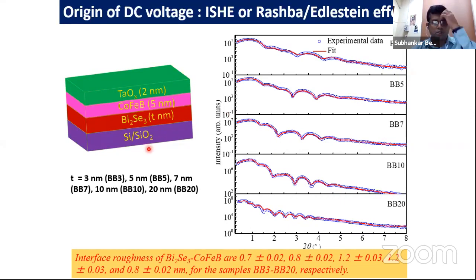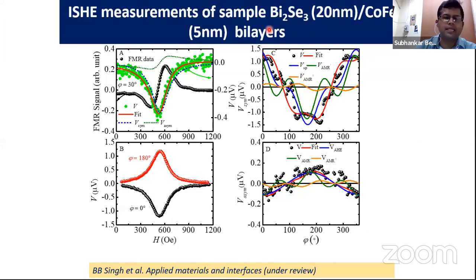And to elucidate that, of course, you need to prepare a thickness dependent study, where we fix the ferromagnetic thickness. Cobalt iron boron is a beautiful material having low damping, and for bismuth selenide, here we have varied the thickness from 3 to 20 nanometer. These are the XRD curves, which show the layers are of good quality. Then again, similar to before, we measure the spin pumping, and as I was saying, at 0 degree it exhibits this voltage, then if you rotate the sample by 180 degrees, the sign should change, and if you go, let's say, to 90 degrees, it should be a very minimal signal because it will cancel out, and that's basically shown here.